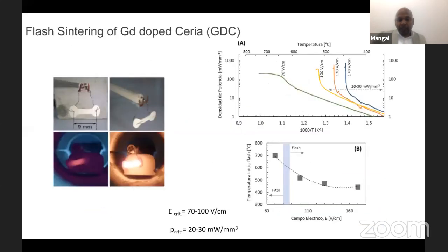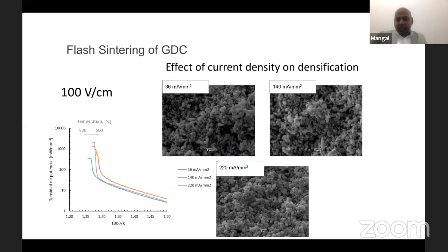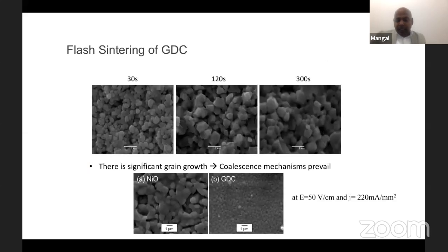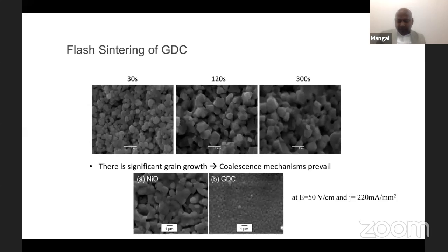Here you can see how the flash sintering occurs. You can see the grain arrangement and grain density, how the sintering occurred with nanograins. So it is possible in a few seconds, though of course it also needs optimization with different applied electric fields and different current densities, and we have to optimize with different times. So these kinds of techniques normally give very good nanostructured materials.